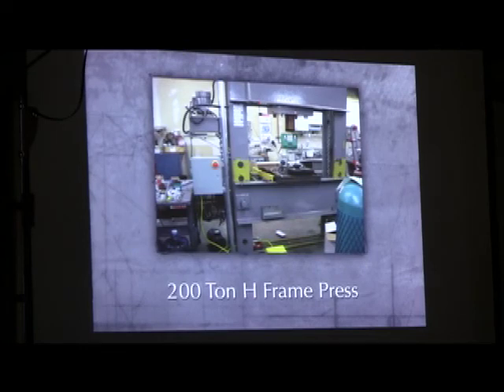So we went from 3.5-inch cans to 6-inch diameter cans that are 30 inches long, not really understanding how hard it was going to be to scale up. When we had been using a 50-ton press before to consolidate things, now we need a 200-ton press to consolidate it. Great deal on eBay, though, by the way. That's a $50,000 press that we got for $5,000. I had to put a little work into it, but not too bad, all things considered.